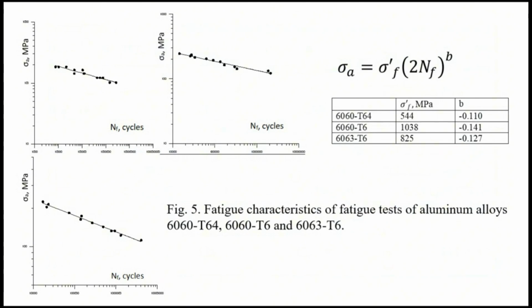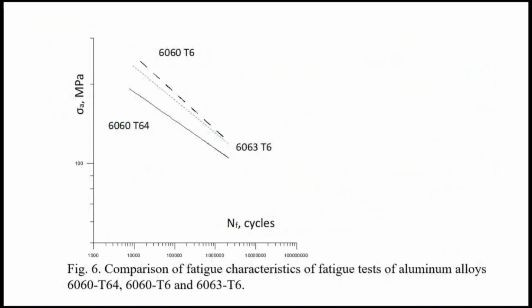So we have put on these photos only experiment for fatigue in bending, because we had impact bending first. Now fatigue bending. We have 3 characteristics, Basquin equation. For 3 materials, we see this characteristic. Now it's very difficult to say what kind of material is better, but you have 3 characteristics with points of experiment. But on the next figure, we put 3 Basquin characteristics without points of experiment, only the characteristic.